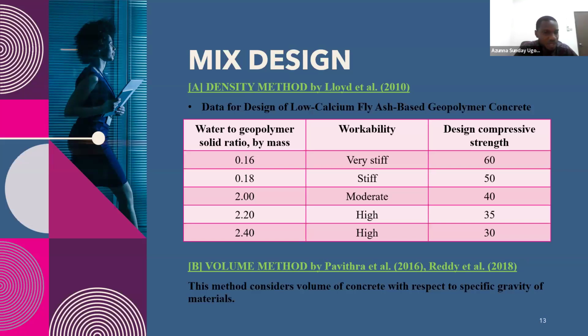So if you want to design using Lloyd method, normally the density of concrete is 2,400 kilograms per meter cube. So you pick that 2,400 kilograms per meter cube, then from there, you now ascertain the percentage of fine aggregate and coarse aggregate that you want for your concrete. So most times, 70%, 78%, depending on what you want. That method doesn't consider the specific gravity of the materials. It also doesn't consider the volume of what you want to cast.